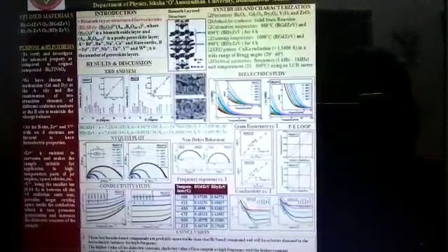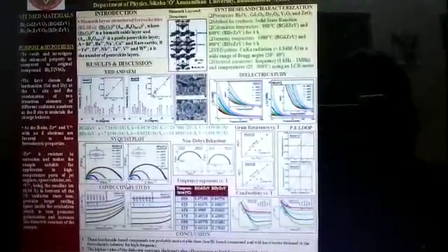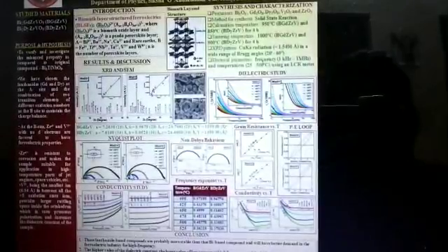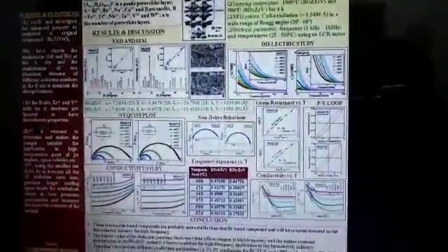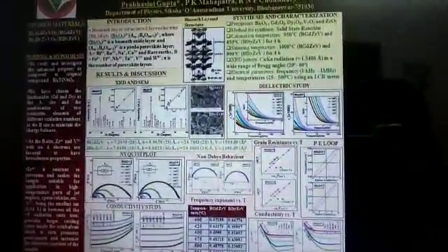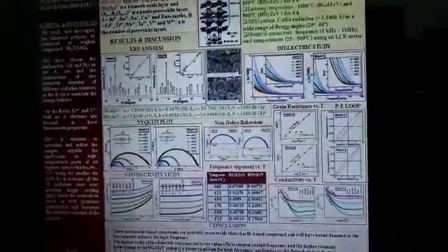Thus, we can say that these lanthanide based compounds are more stable than the Bi based compounds and will have better demand in the ferroelectric industry. Further, the higher value of dielectric constant, low value of tan delta and the higher remnant polarization of BGdZrV makes it a better candidate.